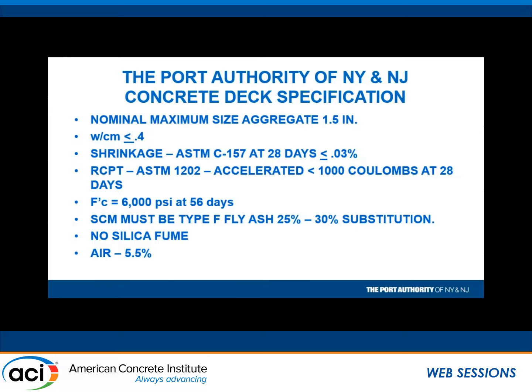So that's our shrinkage requirement. Rapid chloride permeability test. Okay, that's what we use for acceptance criteria for bridge decks. And what was interesting when we got in on the Goethals Bridge, the reluctance to do this test during production, that we should just do this test once for the mix design, hold it in our hip pocket, and assume nothing's changed. And I said, well, if we do that, let's not do any testing. If you believe that people are going to tell you when anything's changed and you don't need to do any testing for diffusion, which is the primary factor for the longevity of the deck, why are we making cylinders for compressive strength when we don't have a problem with that on none of our jobs?